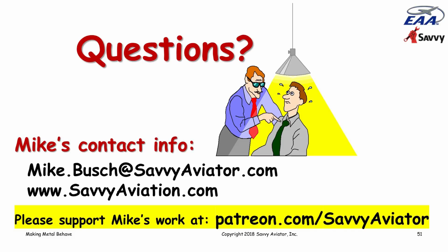Okay. Keith is wondering, does the annealing, hardening, and tempering process work with alloys of aluminum also? Yes, it does. As I said, it's done at lower temperatures than the ones we were talking about with steel, but it absolutely does. And aluminum is routinely heat treated. As I mentioned, the most common material that we use in aircraft structure is 2024 T3 Alclad, and the T3 is the code that talks about both the heat treat and the cold rolling, both of which are designed to harden the material.